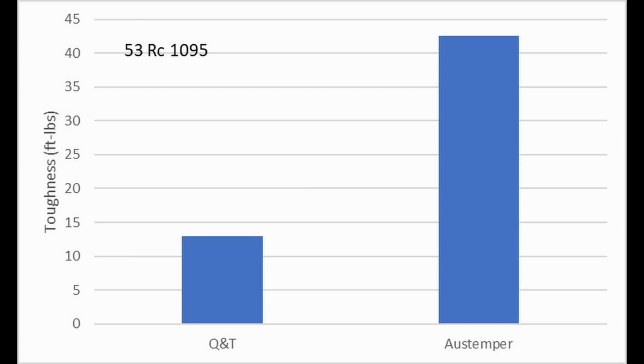So here's a chart that is in a bunch of ASTM handbooks, and it shows that 1095 at 53 Rockwell, with a normal quench and temper, they got around 13 foot-pounds in a toughness test, and with an Austemper, they got over 40. So like a 3 times increase in toughness. Now, why would it be that Bainite would be so much tougher than tempered martensite if they're so difficult to differentiate, except for with very fine microscopy?